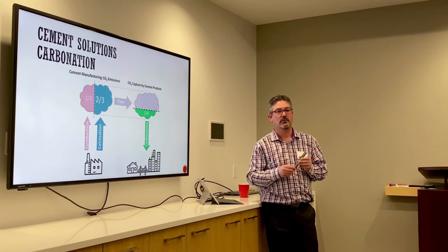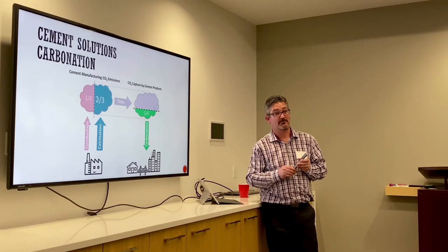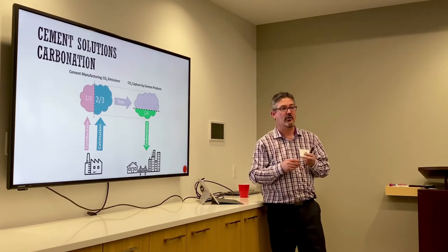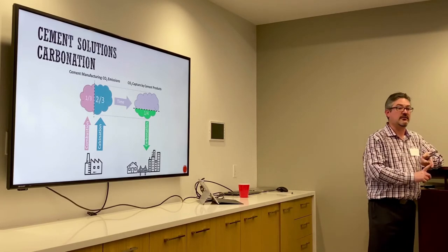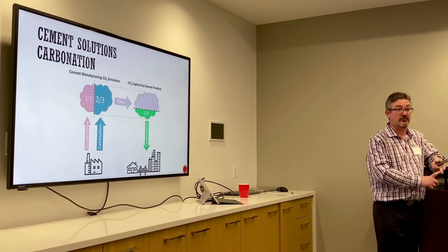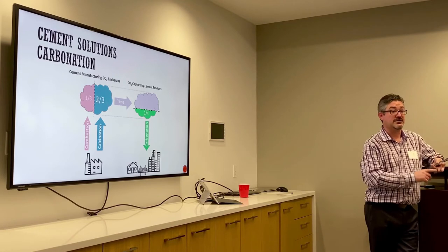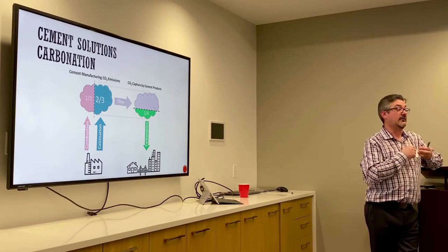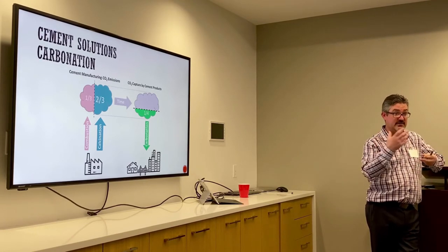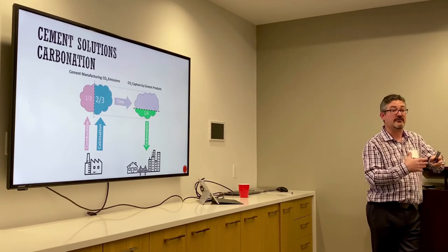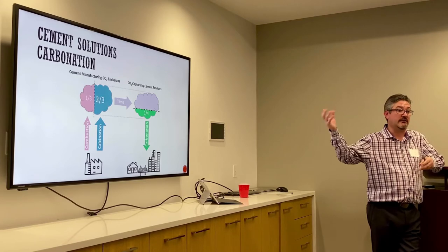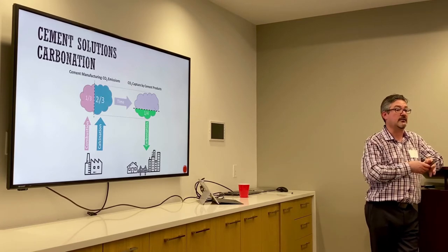How many years does this carbonation process take? A long time. Now, there's a whole bunch of different factors that affect carbonation. There's things like the weather conditions, the atmospheric CO2 concentration, temperature, age, surface area, because everything has to be absorbed through the surface of the concrete, surface treatments, all of those sorts of things affect how much CO2 is actually going to be absorbed back into the concrete.